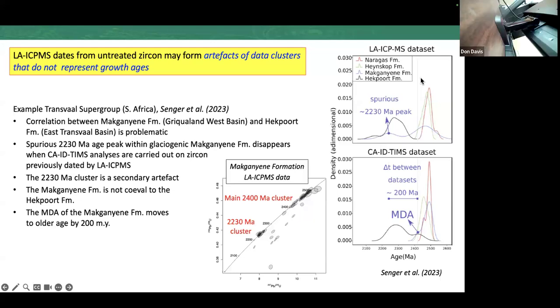But I would like to emphasize the importance of using BSE imaging, especially for old zircons, because alteration under BSE, which is what you're trying to avoid, is dark, whereas the high uranium parts, which host the alteration, are bright. Whereas it's the opposite with, as you know, CL. And in places like China, they do exclusively CL, no BSE whatsoever. So if you have an old zircon, you really can't distinguish the alteration from the high uranium areas. So I like to look at, well, preferably BSE, but ideally both.